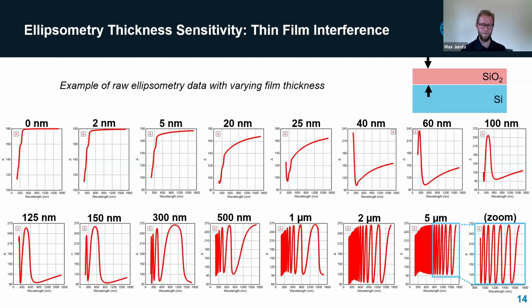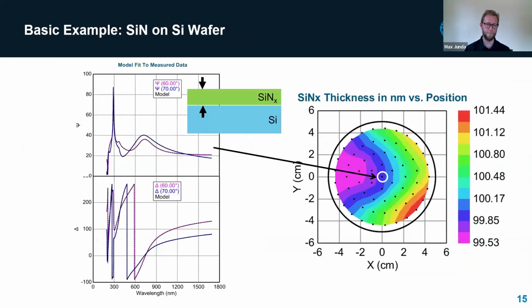So we'll go to the next slide, Lyle. So I figured I would start with a nice basic vanilla happy case that works well. So here is a film. It's a silicon nitride film that is deposited on a silicon wafer, and it's a thickness of approximately 100 nanometers. And so this is right in the meaty zone. This is where ellipsometry does really well.